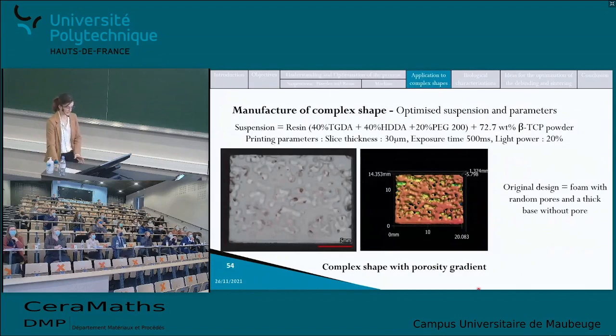And here it appears that it was possible, with the optimized composition, to print such a part. So here the base was actually dense, and the different porosity could be printed, and the part could be cleaned easily. However, there is still some work to do on these parts because there are still some cracks and delamination that seem to appear on the samples. But this result is very encouraging for the future development of this process.